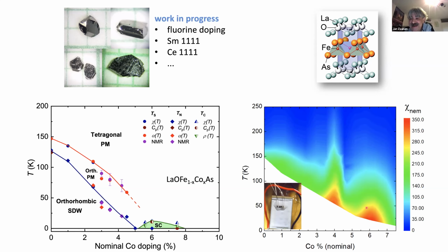when you have the lattice and there is disorder, right? You do expect that you get a sort of puddling, which is just silly, you know, having kind of orthorhombic domains that are messy. Right, so where you could switch off the electron-phonon coupling, it could be that you would have a very neat second order electronic nematic transition, but in fact obscured because you see it indirectly through the lattice, and the lattice feels a lot more about its disorder than the electron system is doing.